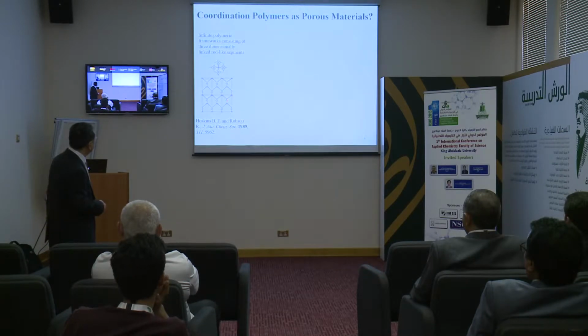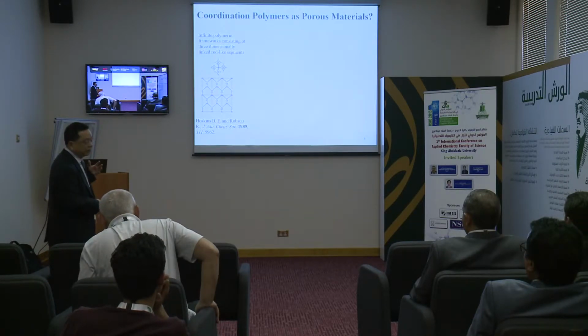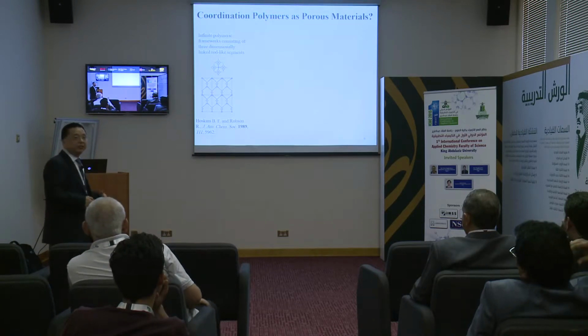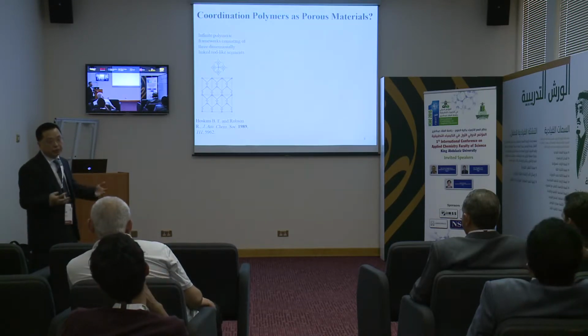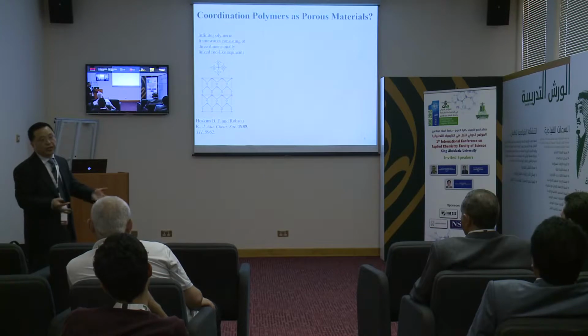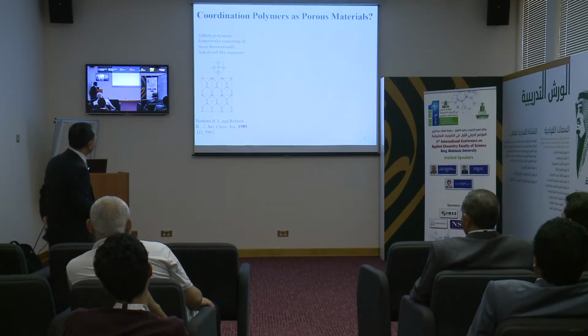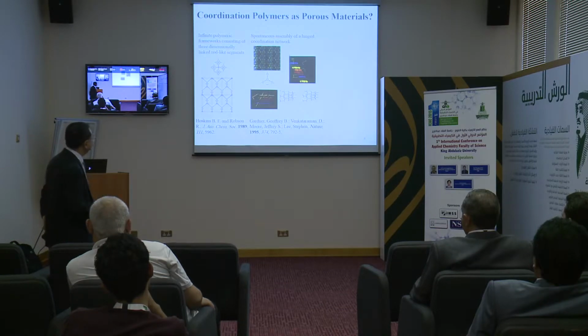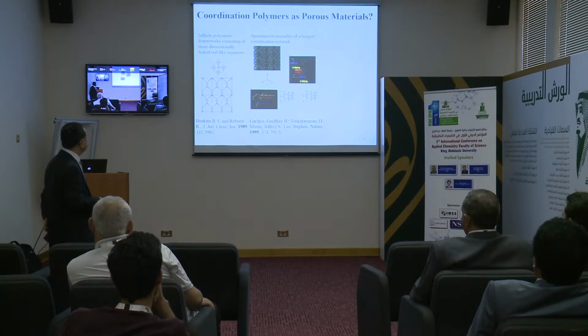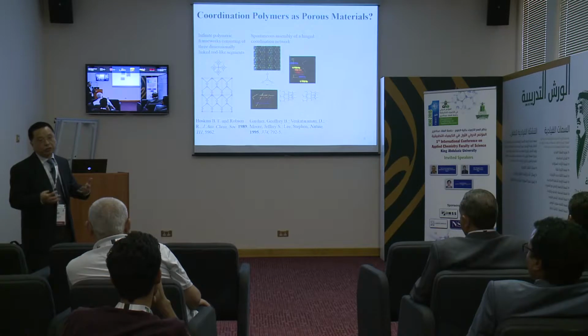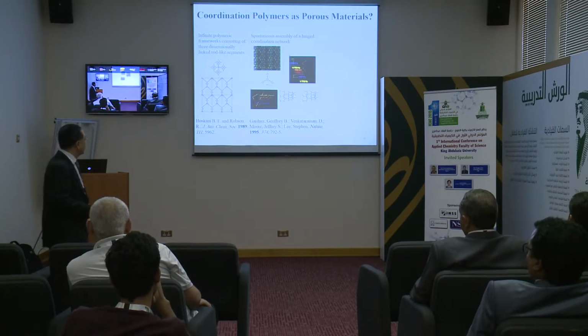At the beginning, because this is structurally porous but not stable, once we remove the solvent molecule, the framework collapses. So there is no gas absorption property at all. At the beginning, a lot of effort went into trying to stabilize the framework. One of the methods is using these pi-pi stacking interactions. And this work is to a certain extent kind of robust, although no gas or vapor absorption has been established.